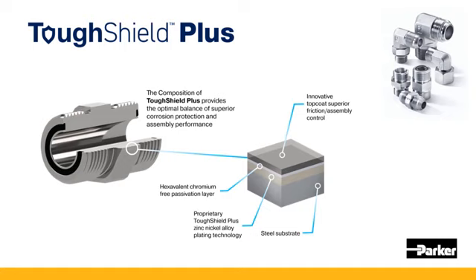Then what comes next is the passivation layer. It's often called the chromium conversion layer or even chemical conversion layer. Those terms are often used synonymously. It's another thin coating that protects that sacrificial zinc-nickel as well as the substrate. So for years, the industry battled with hexavalent chromium passivation or hexavalent chromium conversion. And about 15 years ago, the end-of-life vehicle directives mandated that we get rid of that in our industry and many industries. So Toughshield Plus continues to be hexavalent chromium free. So just to be clear about that.